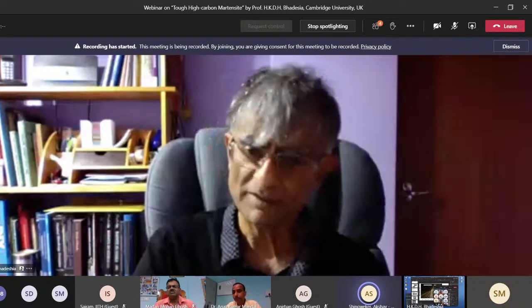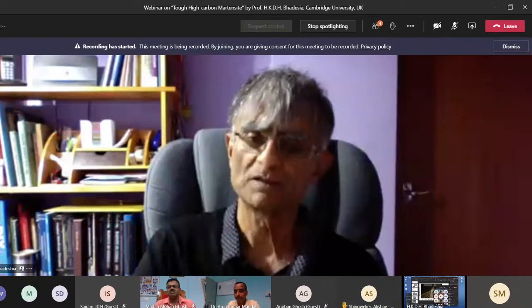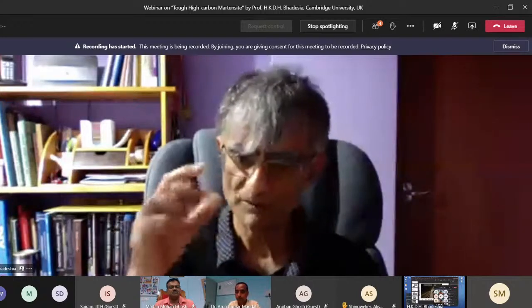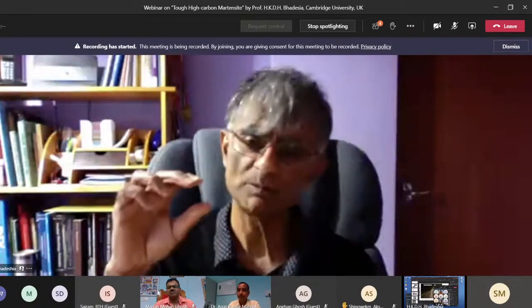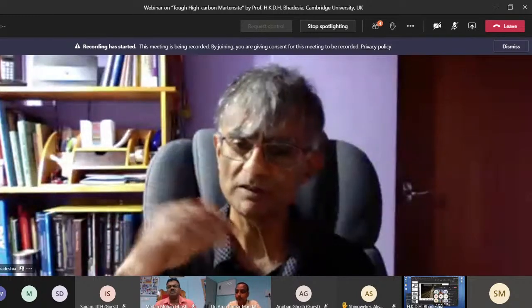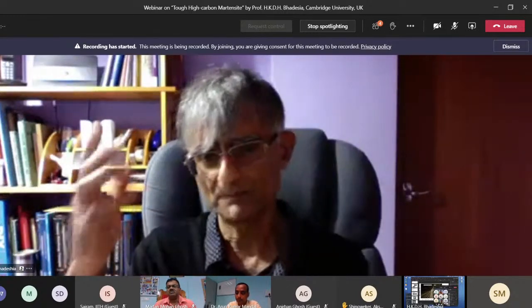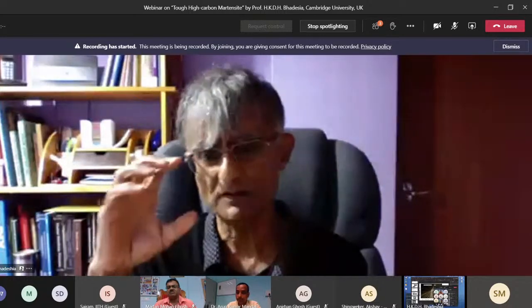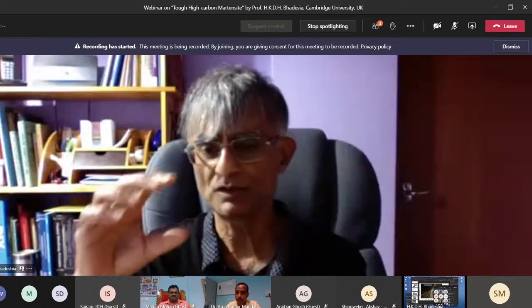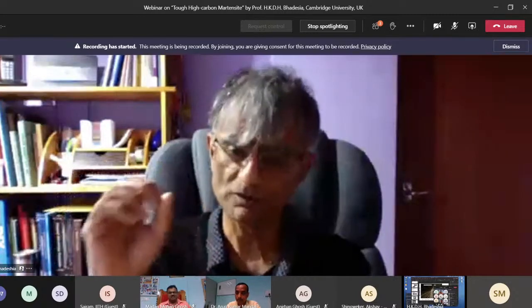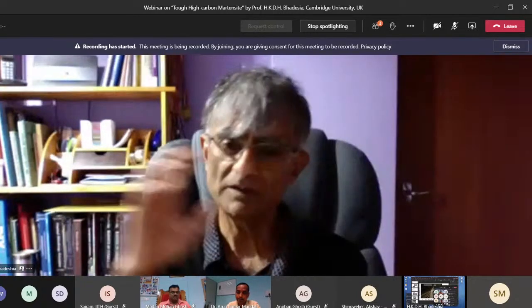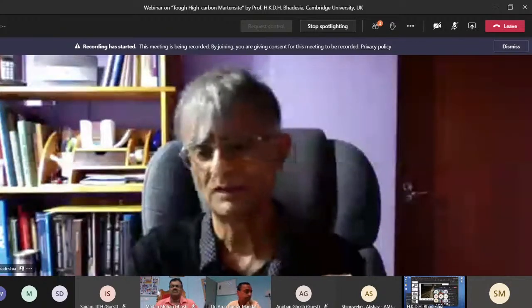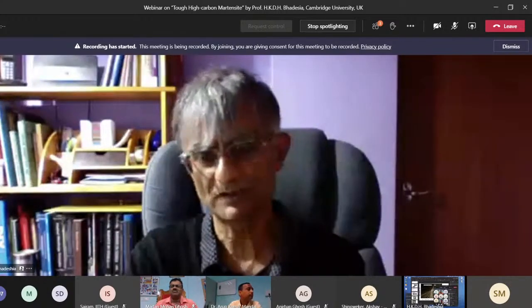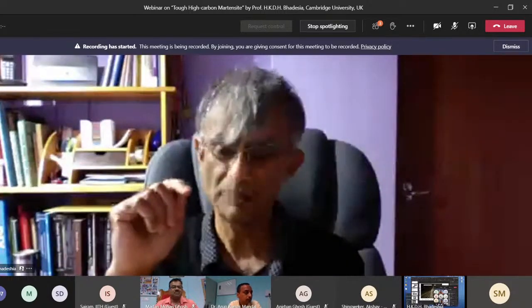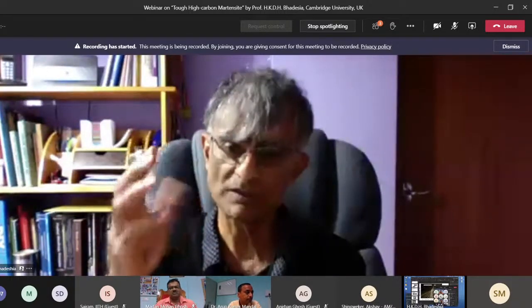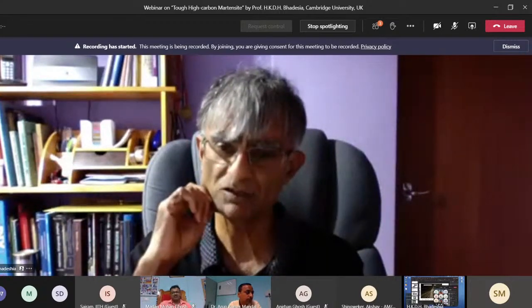The very best way is X-ray diffraction, because a conventional X-ray diffraction will penetrate about 10 micrometers of the steel and give you a quantitative assessment of the retained austenite content. And if you want a greater depth, then you can either use synchrotron X-rays or neutron diffraction. In the particular steel that I was talking about, there is basically zero retained austenite, but there are many armor steels where you need to look at austenite, and the best way is X-ray diffraction. Does that answer your question?